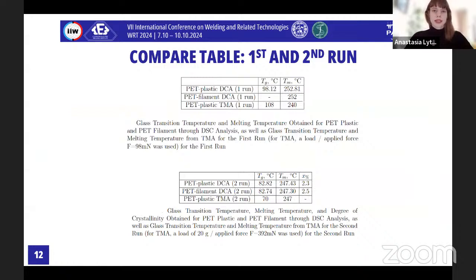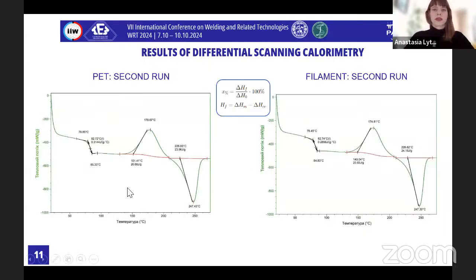For DSC analysis, a PET plastic sample weighing 14.9 milligrams was used in the first run. For raw PET, the glass transition temperature was recorded as 98.12 degrees, and the melting temperature was recorded as 252.81 degrees. And in the second run, which we see in the left graph, for raw PET, which is equal to the extrusion process temperature, the glass transition temperature was recorded as 82.72, and the melting temperature around 247 degrees, indicating that the values remained relatively unchanged after the removal of internal stress.